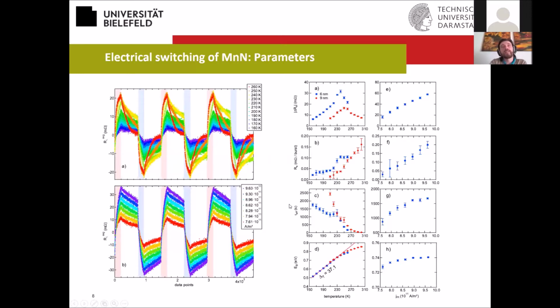And then we look at the relaxation times and compare the 2 different film thicknesses and find that they are pretty similar. And by using the Néel-Arrhenius equation, we compute the energy barrier, and we observe that the energy barrier is basically the same for the 2 films, for 6 and 9 nanometers, which is a bit surprising actually.